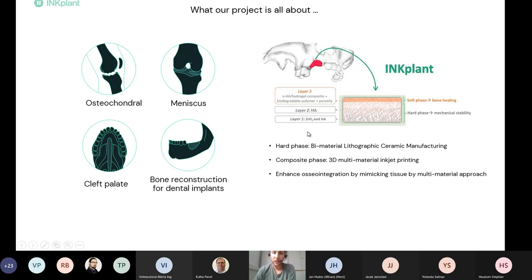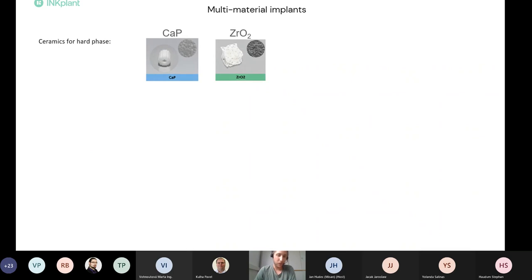So, as I mentioned, the hard phase is produced by a lithographic ceramic manufacturing process by our project partner Lithoz. At Profactor, we are developing the process for multi-material inkjet printing of the composite phase, and combining these two approaches should enhance the osseointegration by really mimicking bone tissue with this multi-material approach. When thinking about the different biomaterials, the term biomaterial is a very broad term, so to say. In the project, we want to cover a very broad range of biomaterials, ranging from calcium phosphate ceramics provided by the company Lithoz to soft materials like hydrogels and synthetic photopolymers.